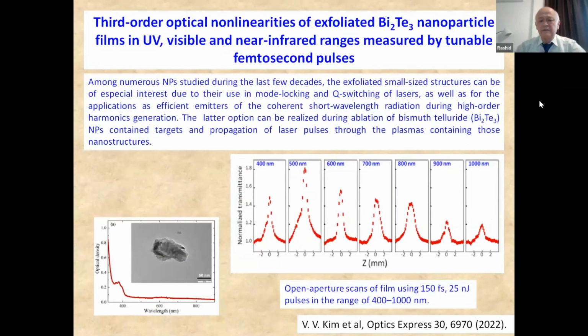Other studies are related to exfoliated nanoparticles. Bismuth telluride is a well-known and developed nanoparticle material. Those exfoliated nanoparticles are used for optical limiting, for mode lockers, Q switchers, and some other applications. However, like in all previous cases, information about them was only in the range of 800 nanometers. We determined that saturable absorption in those exfoliated nanoparticles becomes stronger in the visible range, particularly for 500 nanometers.